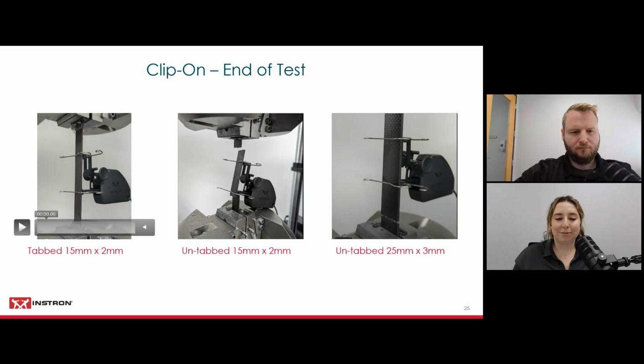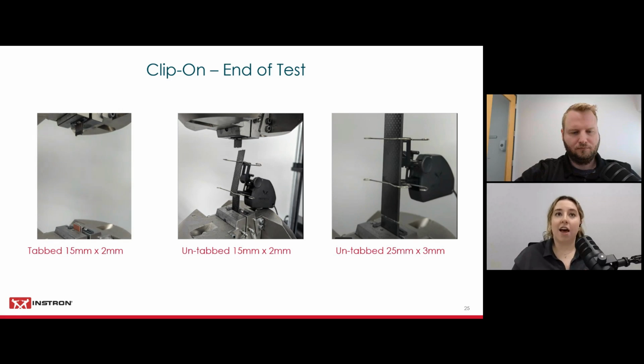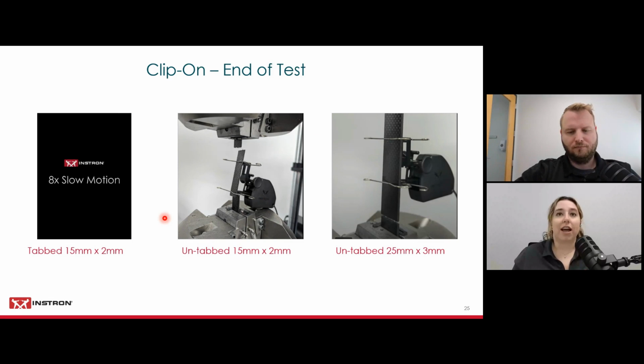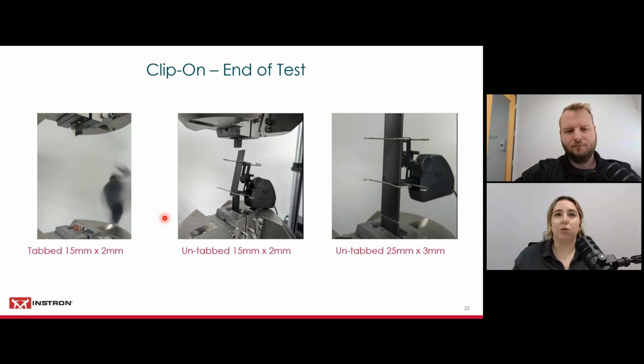But the tab specimens were the ones that I actually tested with first, and I experienced those high explosive breaks. And even though my clip-on fell onto the base of my frame, there were no visual indications of it being damaged, and I was able to use it for the rest of my testing without any problem. Now, something that customers do, they either attach some kind of cord, or they even use the cabling that comes off of the extensometer, and they attach it to a magnet or some kind of holder on the column cover of the frame. So if you do have explosive failures, that cord will catch the extensometer before it falls and hits the ground.